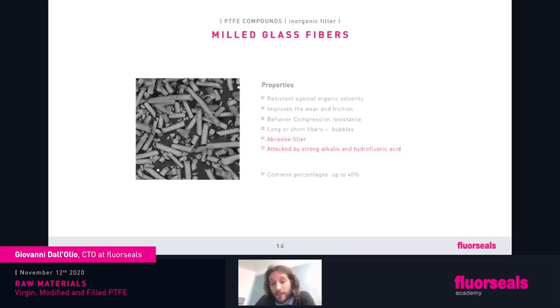But glass has also some weak points. It's an abrasive filler, so glass is really hard. We have mentioned that the wear is improved, so if we're using a dynamic application, we will have a counterpart, but if the counterpart is too soft, the counterpart will suffer wear. So bear in mind on dynamic applications, glass is really suggested because the performance is great, but we always have to think about the counterpart. Better a hard metal when we are making a glass-filled PTFE.